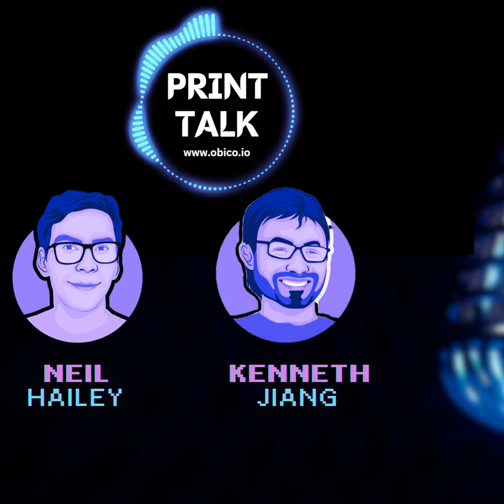Your printer needs to be able to handle the heat and the potential for wear on them. Okay, so walk us through the essentials. What are the must-have features for a nylon-ready printer? An all-metal hot end is non-negotiable. Standard PTFE-lined hot ends just can't handle the high temperatures required for nylon, which is typically printed between 250 and 280 degrees Celsius.